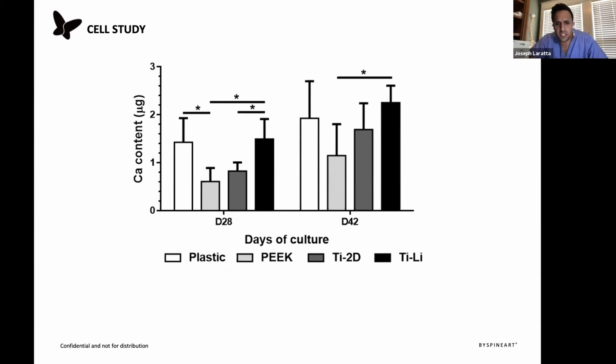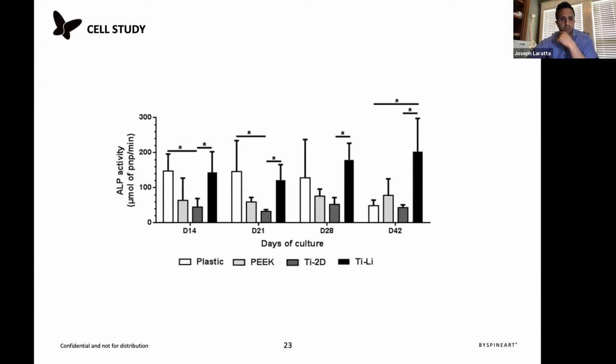The calcium content of the cell culture was looked at as a potential predictor of biomineralization. What we can see here is that the calcium content at day 42 may be slightly higher than the other implants. This is a little bit confusing for me because, given the higher number of differentiated cells in the Ti-Li sample, it's really hard to tell if this is truly an increased calcium content or an increase that's a result of the increased number of differentiated cells. So I hold a little bit of weight in this.